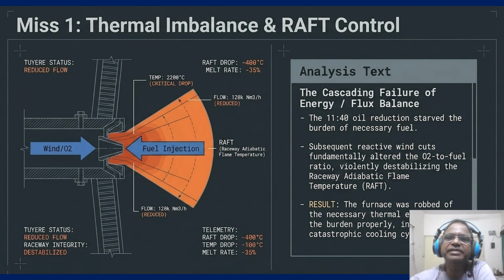So the operational impact is a catastrophic cooling cycle. When you drop by 400 degrees centigrade, your melt rate is not just slower, it's insufficient to keep the slag in a liquid state. The furnace was robbed of the thermal energy required to process the incoming burden. You cannot unilaterally cut fuel and expect the thermodynamics of the lower zone to remain stable. These thermal failures led directly to a chemical crisis in the slag, which destroyed our drainage mechanism.